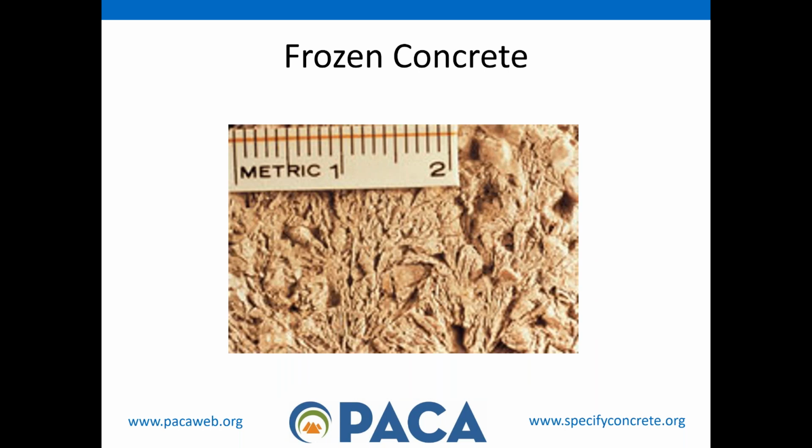So let's talk about cold weather concrete. The most extreme will be the occasion if we freeze concrete. That's really, really difficult to do. We'll show some examples of some people doing it, but that's hard to do. You don't have to freeze concrete to make it weakened, but it can be done. One of the telltale signs of frozen concrete is you look at the surface, and the surface looks like a dried out fallen leaf, all wrinkly with all sorts of little lines and patterns in it, a dried out lake bed, whatever analogy you want to use. Very distinctive appearance to the surface.